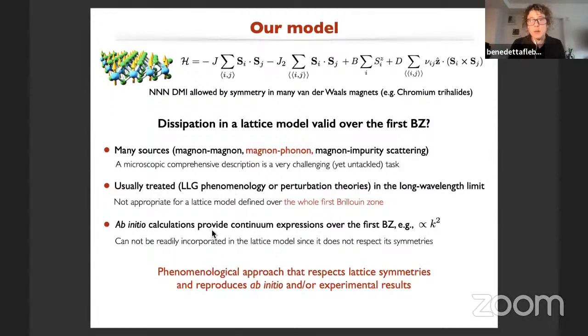Turned out that there is, but there is a caveat. For example, there are some ab initio calculations that provide continuum expressions for the broadening over the first Brillouin zone, but indeed these expressions are continuum, so they cannot be readily incorporated in the lattice model because they do not respect, to start with, the translational symmetry of a lattice model, and in this case, for example, the C3 symmetry of this model. So what we decided to try out is a phenomenological approach that respects the lattice symmetries, and then we try to fit our phenomenological ansatz to some ab initio or experimental results.